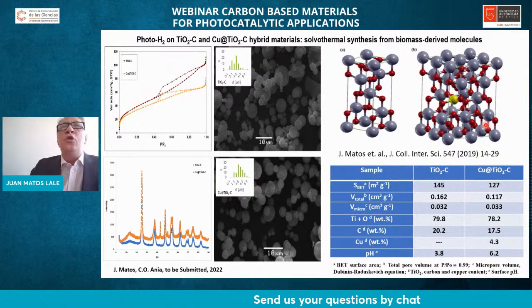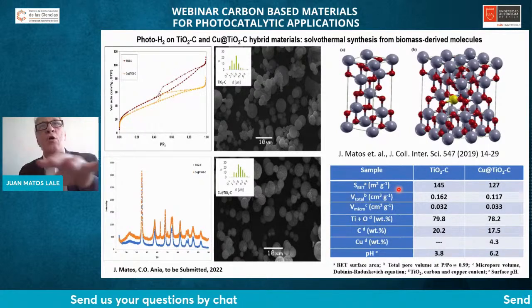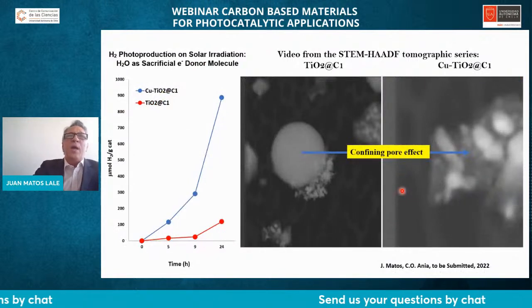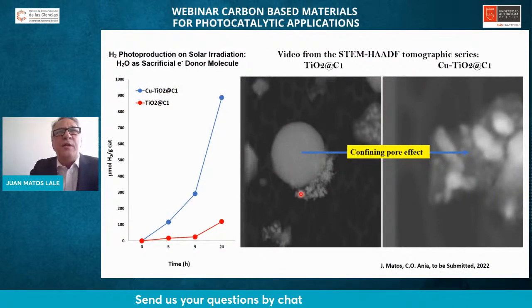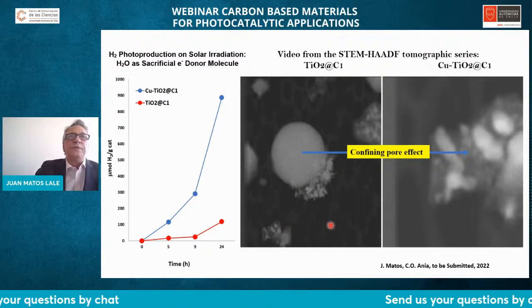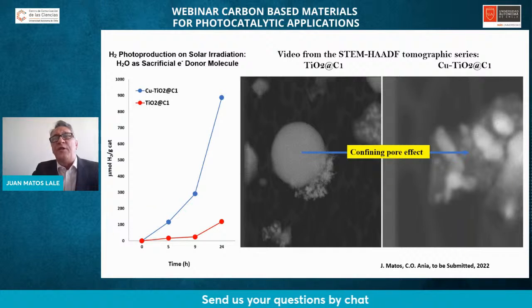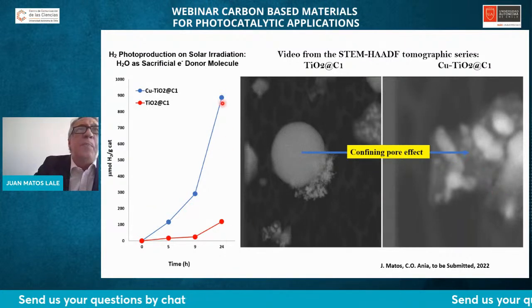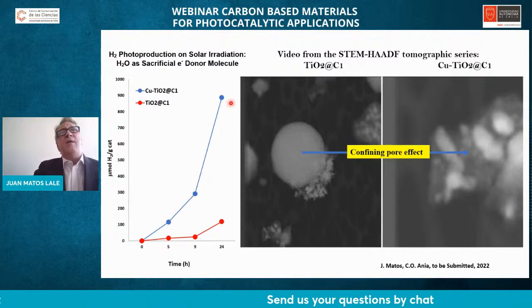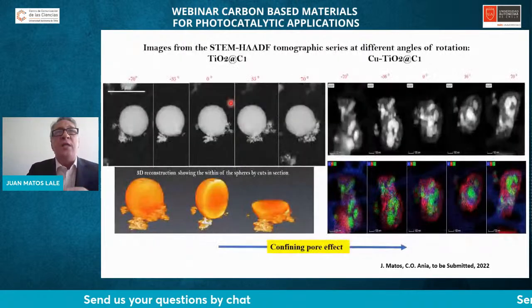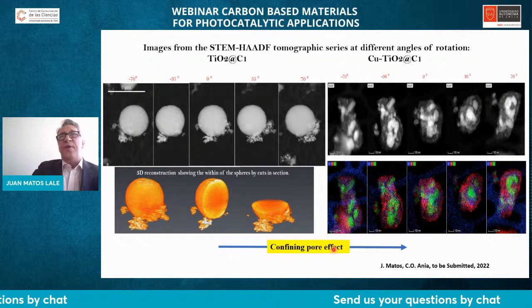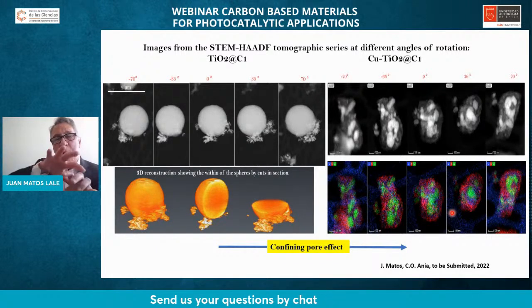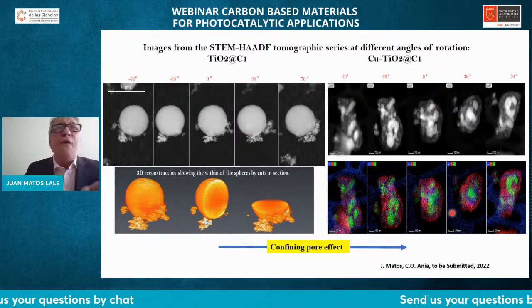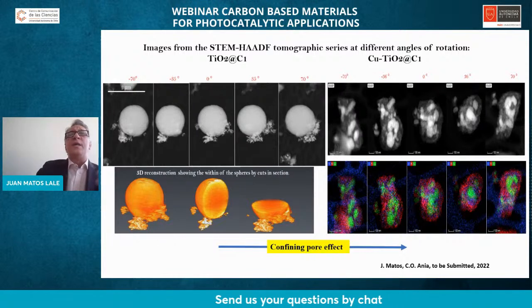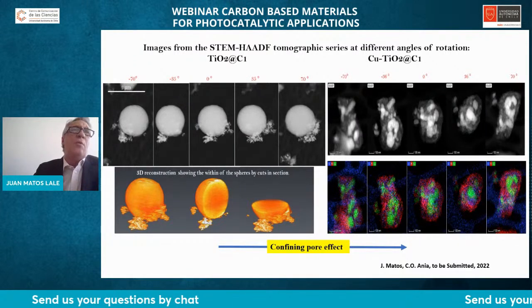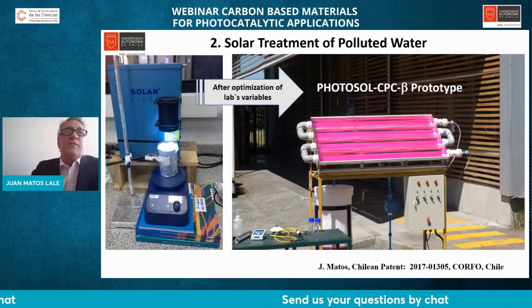With that in mind, we constructed a new kind of material, but instead of carbon alone, we are doping at the same time with carbon and copper. And with carbon and copper, we were able to produce very ordered materials in the case of titanium dioxide and very highly distorted species for copper doped materials. But the important thing here is that in the presence of only 4% of copper, we were able to increase the hydrogen production by a factor of 9. That means with the confining pore effect. In other words, if copper is protected by an important layer of carbon material, it does not suffer leaching or oxidation. So that's a very interesting result that we are about to publish in the following weeks or months, because it depends on the time we can get free.